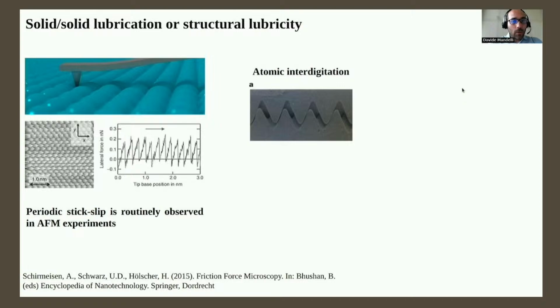Now, the specific topic I will deal with is that of solid-solid lubrication, of structural lubricity, which is the possibility of obtaining lubrication or controlling friction between dry crystalline interfaces. Now, even between crystalline interfaces, the main source of dissipation is due to this type of very abrupt stick-slip motion, where the slider moves ahead in sudden jumps. And these, at the nanoscale, can be interpreted in terms of atomic interdigitation occurring between the two contacting crystals.